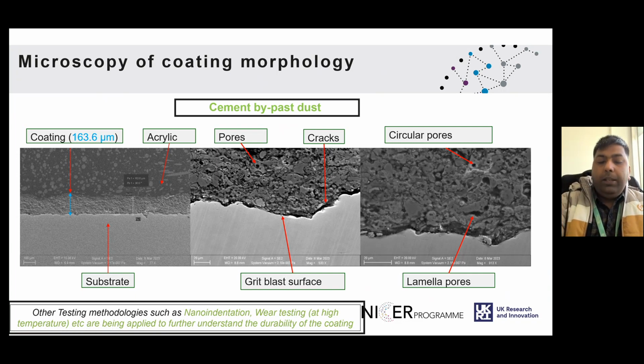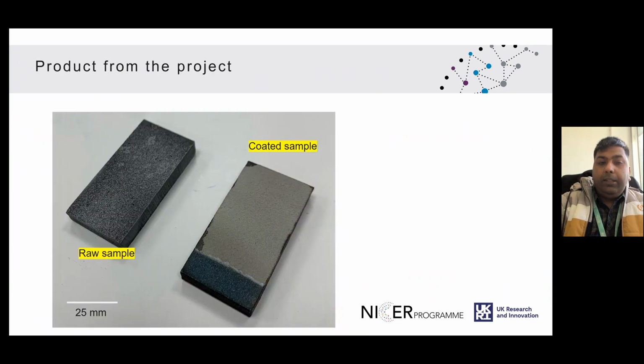So overall, what we aimed to achieve was achieved indeed. What we can see here, that raw sample was sand blasted, and the coating was subsequently deposited, which is clearly shown here. And through this study, we aim to enable recycling of the cement bypass dust. So on that note, we are still continuing this study further. And as the results start to come out in more intensity, we aim to generate scientific publication out of it.